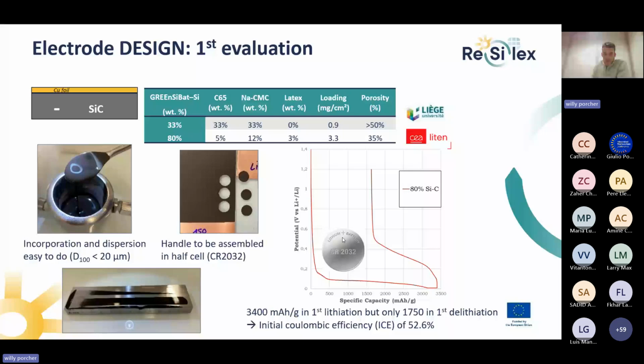So the first coin cell results are still versus lithium. We are versus lithium at 0 volts, and so you start from these potentials. The alloying is in this plateau, and here you have the delithiation of the cells. The specific capacity is per gram of active material, and you can see a very huge capacity of the composite provided by University of Liège.